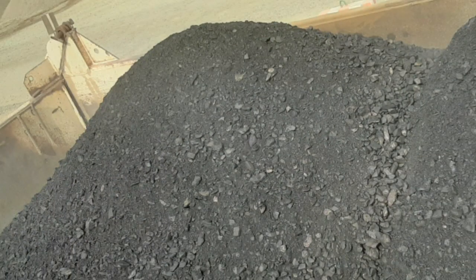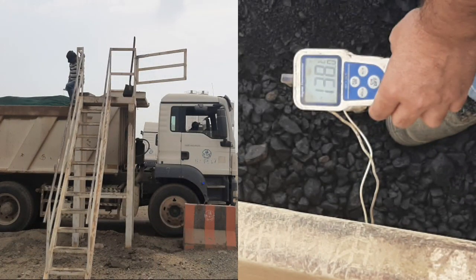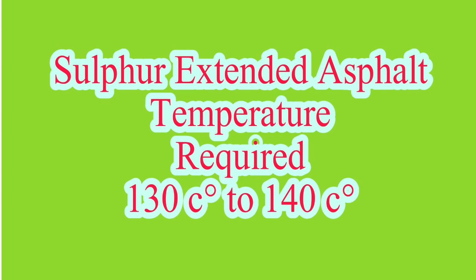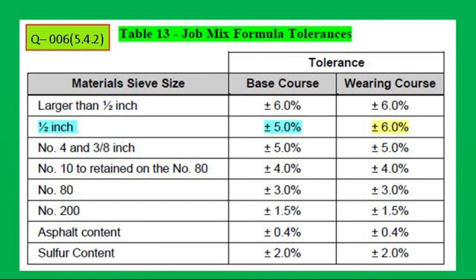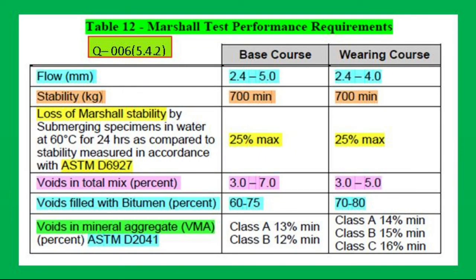Calculate the batch weights by the new percentage and put all new weight values into the operating system. Mix again two tons and discharge in the truck, then check visually. If the asphalt mix is good, continue production and wait until the truck is fully loaded. After the truck is loaded, stop the truck at the sampling point and take samples according to Aramco standard for extraction, sieve analysis, and Marshall properties. After testing in the laboratory, review the report for extraction and sieve analysis according to Aramco standard, and review the report for Marshall properties according to Aramco standard.